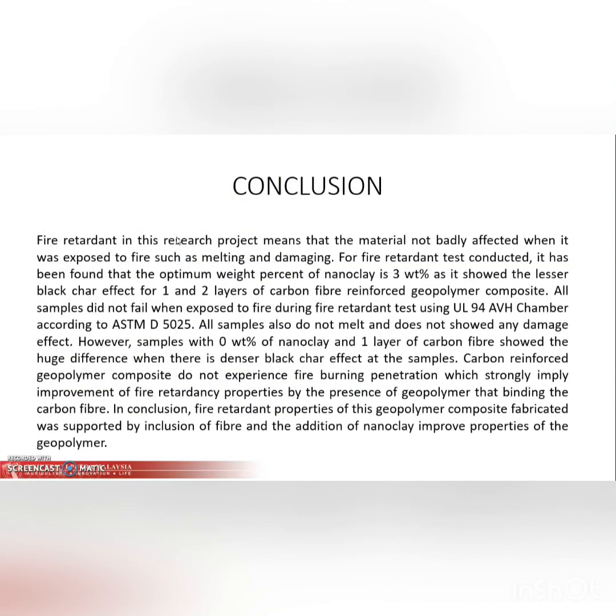For the fire retardant testing, we have reached the conclusion. Fire retardant in this project means that the material is not badly affected when exposed to fire, such as by melting and damaging. For the fire retardant testing conducted, it has been found that the optimal weight percent of nanoclay is 3% as it showed the lesser black char effect for 1 and 2 layers of carbon fiber in the geopolymer composite.